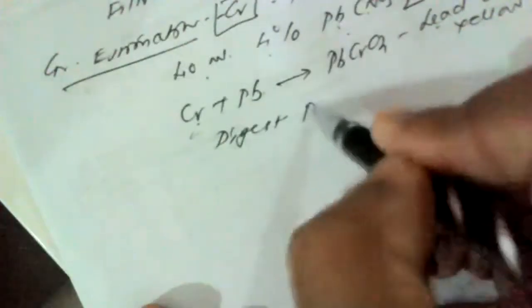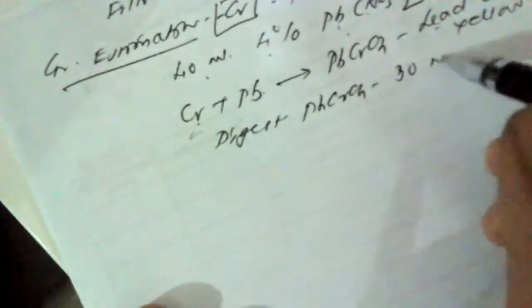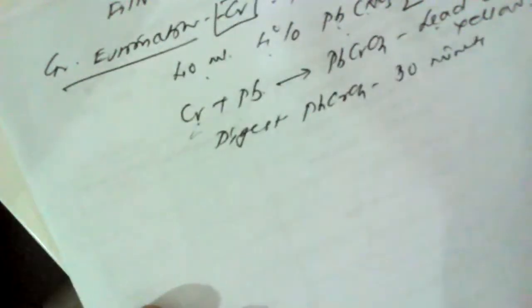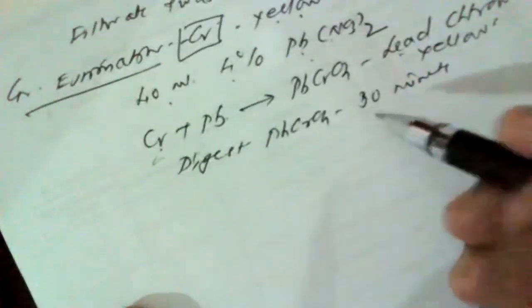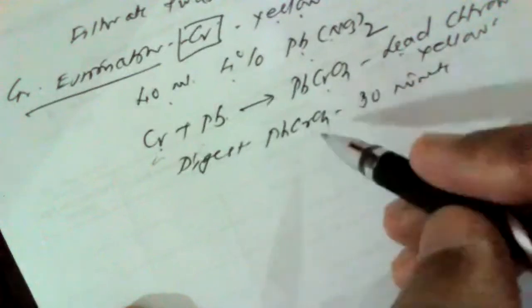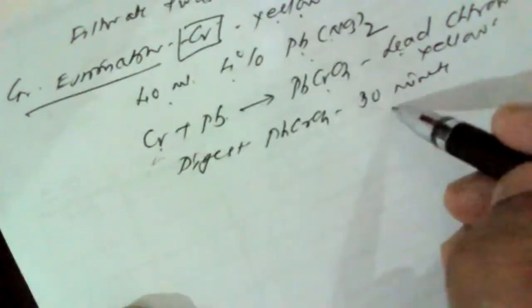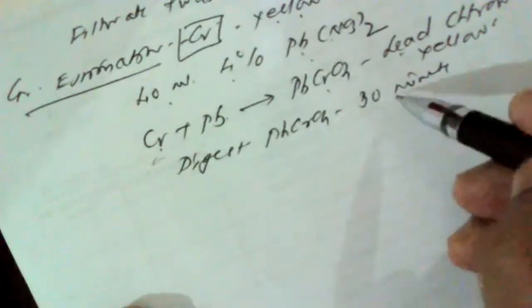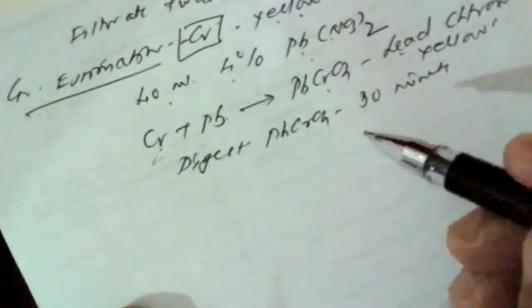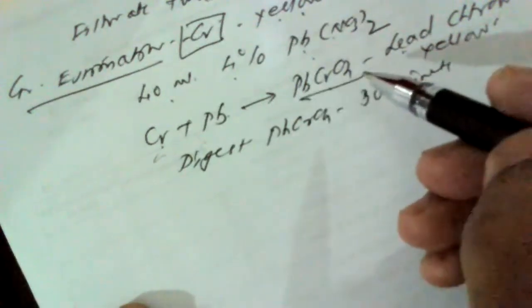Now we have to digest this precipitate of lead chromate for around 30 minutes. What is the digestion procedure? We have to heat the precipitate along with the mother liquor for about 30 minutes on a sand bath or on a water bath. After 30 minutes, the supernatant liquid in the beaker becomes clear, and at the bottom we will obtain the crystals of lead chromate.